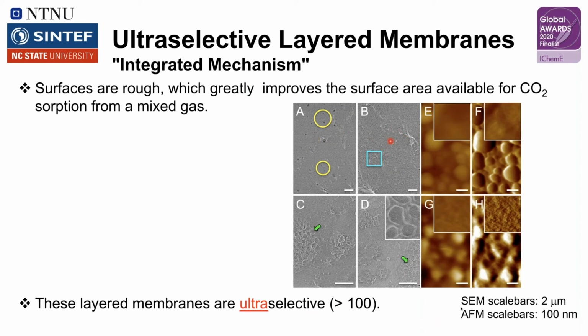To give you an idea of what this looks like, here are some SEM images showing before and after our coating on top of the Teflon amorphous fluoropolymer. And you can see that initially we start off with a few holes here and there, but over here, what we're seeing now is a pretty conformal coating. For PDMS, we start to see some regions that show that the surface is not exactly homogeneous, but upon closer examination by AFM, we can certainly see that there are nanoscale droplets of our coating on the surface. And now this provides a very rough surface where we have these CO2-philic groups available to capture the CO2.